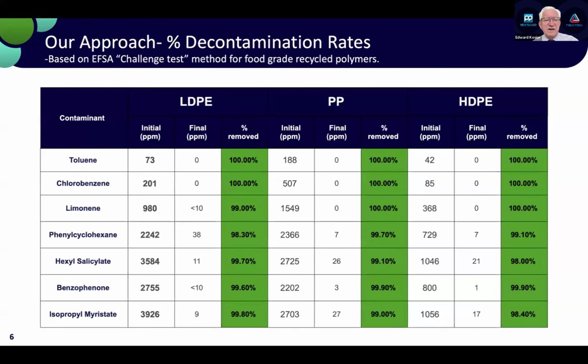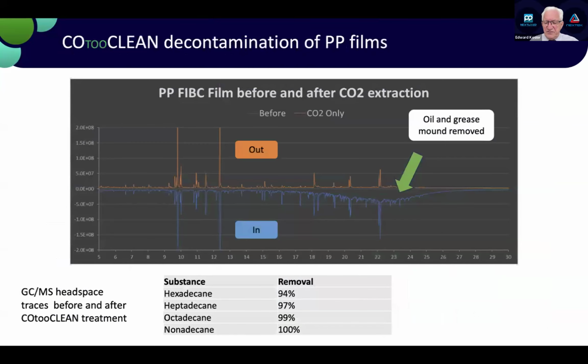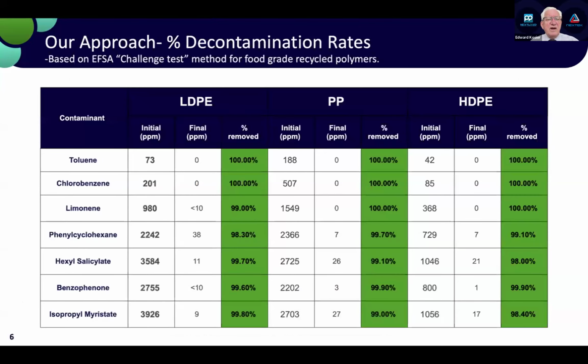And in this case, what we do is we have a list of what we call surrogate contaminants. These are chemicals that we apply to the polymer in a solvent-based system. So we pre-contaminate film, and then we actually put the contaminated material into our process and then look at the decontamination rates. So we can see that for example, on the left-hand side, you'll see toluene, chlorobenzene, limonene, phenylcyclohexane, hexyl salicylate, benzophenone, and isopropyl myristate. These materials are added to the films at levels typically targeting 1,000 parts per million. In some cases, we've gone higher.